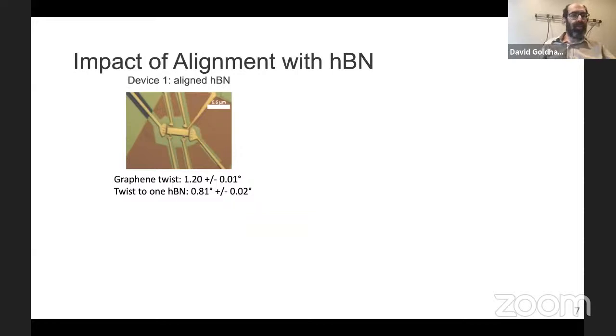I'm now going to depart from the historical structure and tell you that we had unintentionally aligned the lattice of this twisted bilayer graphene with the lattice of the cladding layers. I just referred to them as a dielectric, but I think you've heard during this summer school that the most typically used dielectric is hexagonal boron nitride. It has almost the same structure as graphene, but a slightly different lattice constant. And it turned out we had accidentally aligned the boron nitride in one of the two cladding layers almost perfectly to the two twisted graphene layers. This was our early attempt to reproduce Pablo Herrero's group's work and to see superconductivity. And as you'll see, we didn't see that. That turns out to be a consequence of the alignment with the boron nitride.